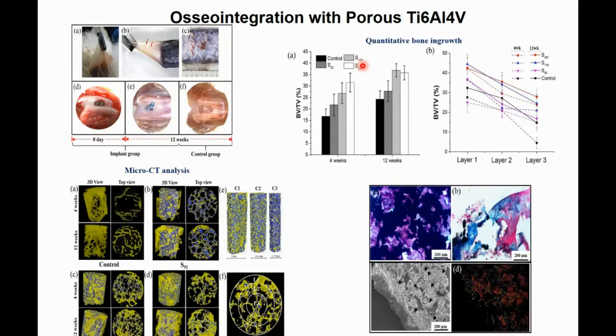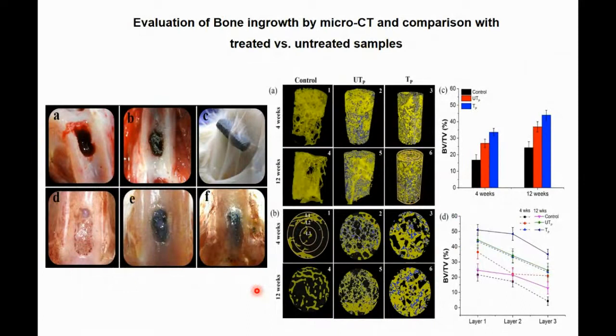As I mentioned here, pore size is very important. Pore size has to be, as proposed by Hulbert, 150 to 200 micron. Actually, this number is very critical because when tissue has to grow into the pores, vasculature has to form. For forming the vasculature, the minimum pore size requirement is 100 micron. But we have shown that if we play with 92 micron, 178 micron, 297 micron pore size, the 297 micron pore size has much better bone volume inside the porous titanium as compared to the 92. We evaluated this with microCT as well as with histological studies, and we have seen remarkable results.